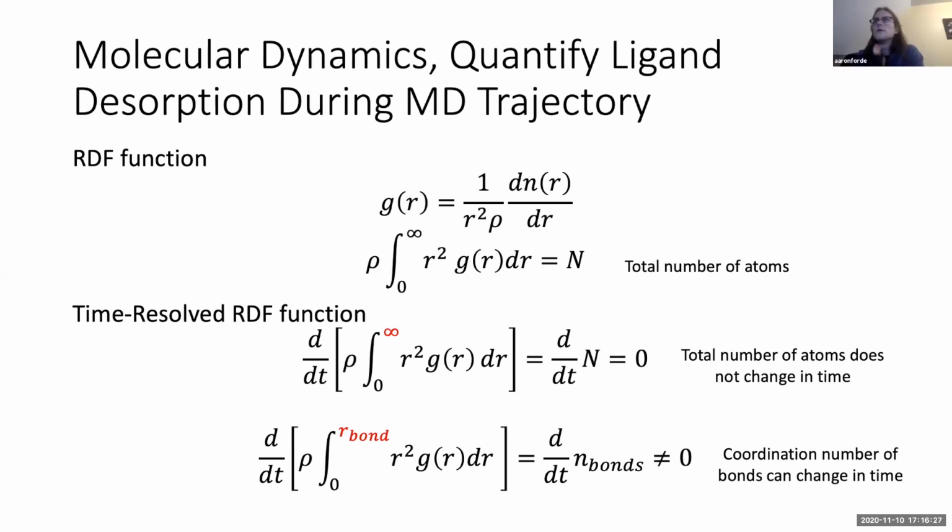And if you do this normalization, it will be approximately a flat line if it is a random liquid or dense gas. And if it is a solid, it will be like sharp teeth. Solids will just be peaks where the atoms are. Okay.